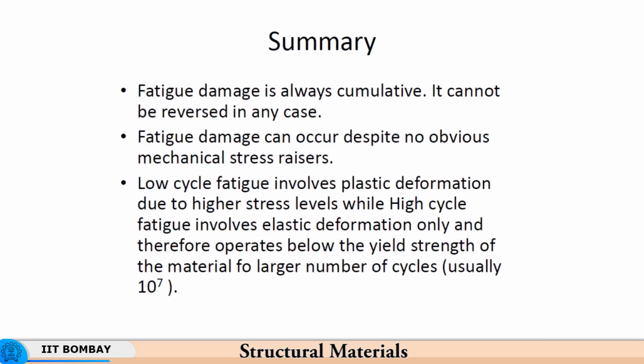So, with this we summarize that fatigue damage is always cumulative, it cannot be reversed in any case. Fatigue damage can occur despite no obvious mechanical stress raisers, that is because you can have metallurgical defects as well. So, although the geometric defects can be eliminated by conscious design effort, the metallurgical deficiencies can result in soft spots remaining behind, meaning the material being weak at different locations, which nucleates a crack, because even in the absence of mechanical stress raisers, the stress magnitude acting on the workpiece is going to cause a greater amount of deformation in the relatively weak zone, and as a result it will have much less ductility, or it will exhaust its ductility very rapidly, and therefore the damage will keep on accumulating.